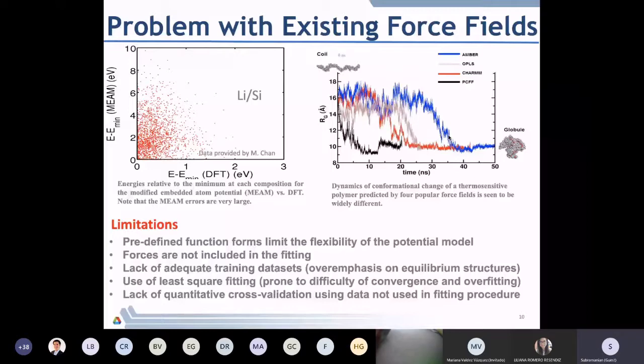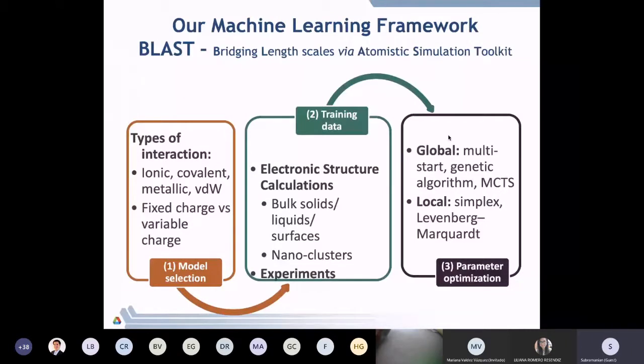So to address these, what we have done is to come up with a framework called BLAST. What BLAST allows us to do is to pick a model depending on the type of interaction, and generate training data. We could either use experimental data if it is available, or use electronic structure calculations to generate training data sets that could be nanoclusters or bulk properties or surface properties and so on for films. And then the third step is parameter optimization. Once you have your model and training data, you could do the parameter optimization using a combination of global and local optimization.